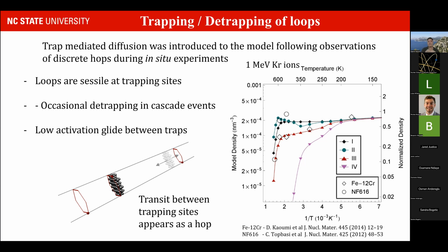By introducing this trap-mediated diffusion concept into the model, we managed to get much better agreement between experiments, and you see the curves on the right. The experiments are the clear dots, and the modeling results.